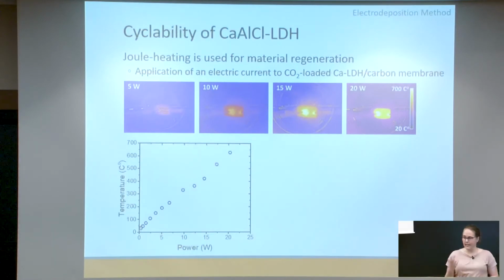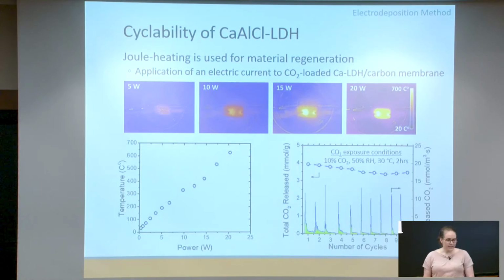Last thing, in terms of cyclability, we did a study using what's known as Joule heating as the regeneration approach. This is where you use an electric current to heat up a material. Because the carbon is conductive, the carbon heats up and the layered double hydroxide heats up at the same time. By tuning the power, you can change the temperature the system is heated to. We did this a number of times after the carbon dioxide was captured, and this is what we can see in terms of the behavior.